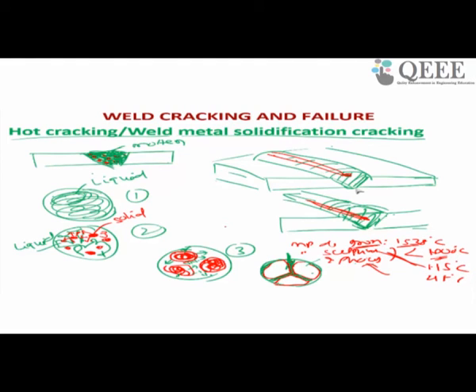For example, iron with sulfur and phosphorus. Sulfur and phosphorus have a melting point of less than 200 degrees centigrade. However, iron has a melting point of more than 1500 degrees centigrade. In that case, you will have this kind of problem, that is solidification crack.